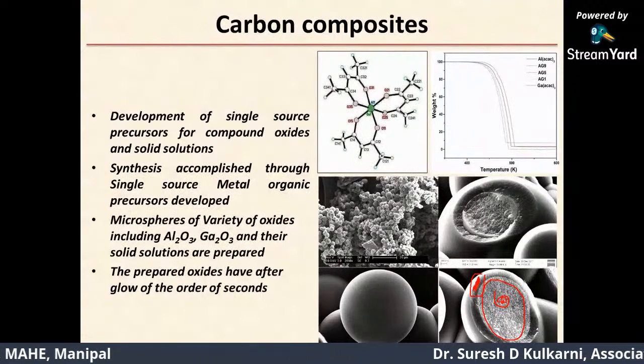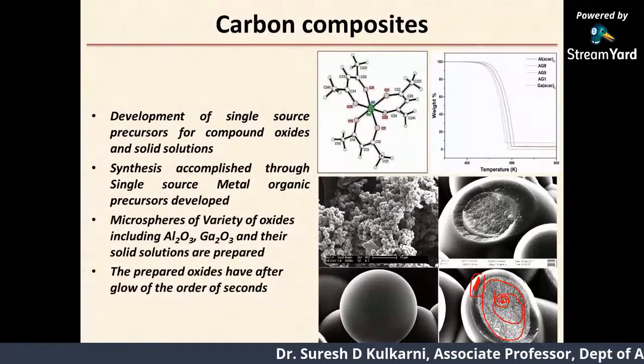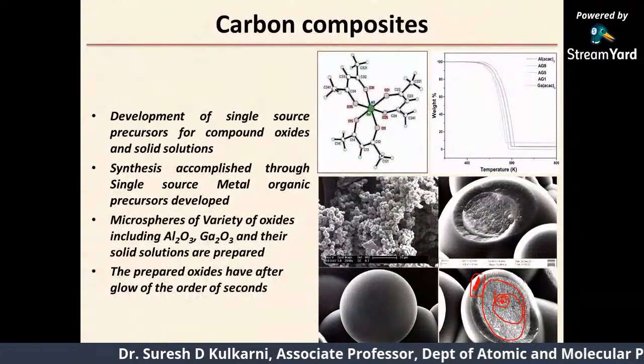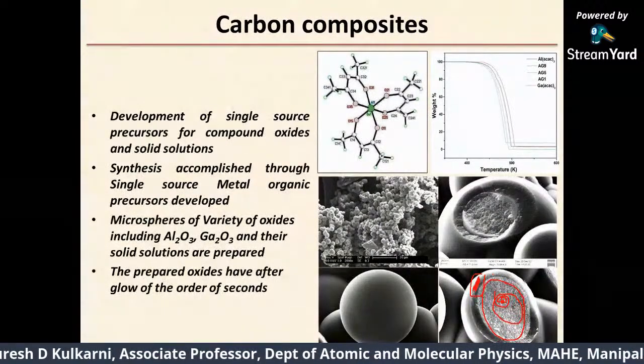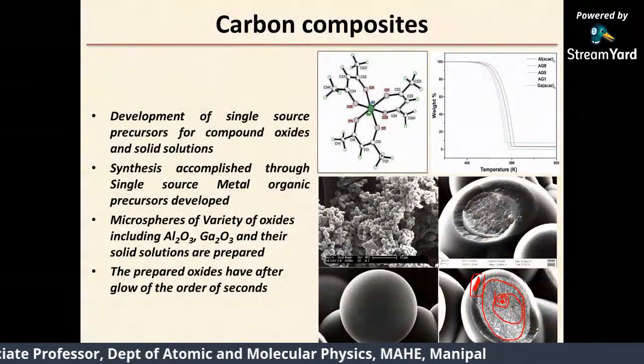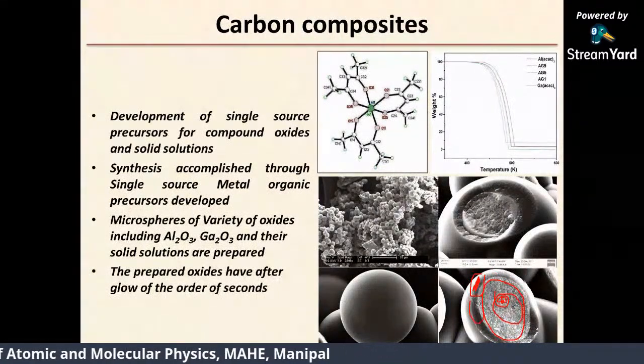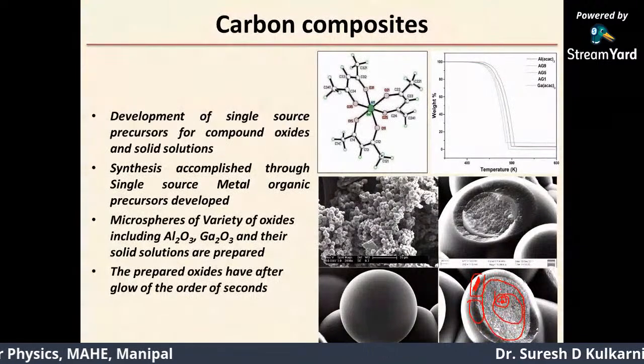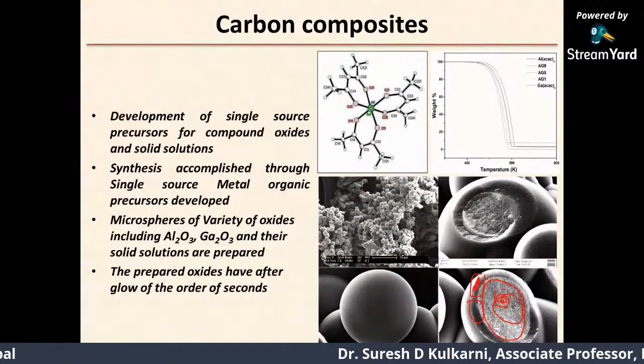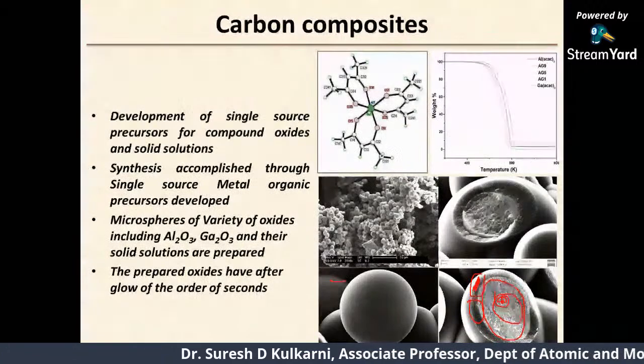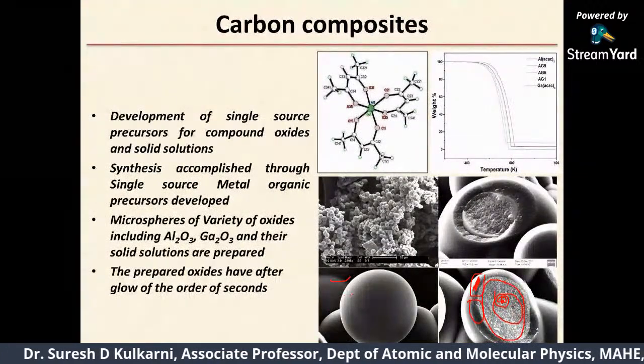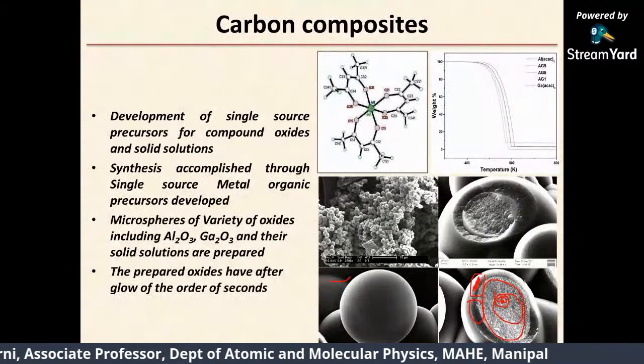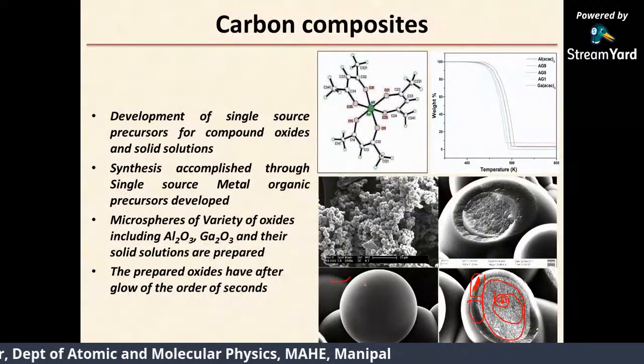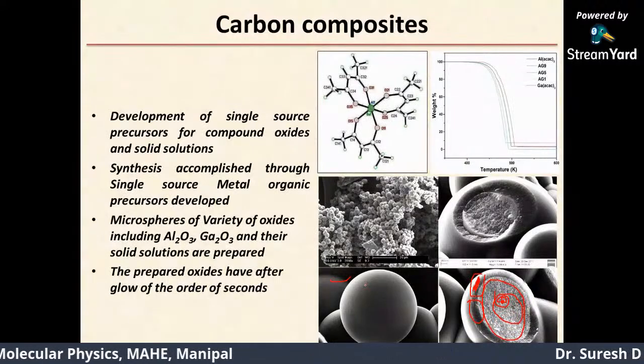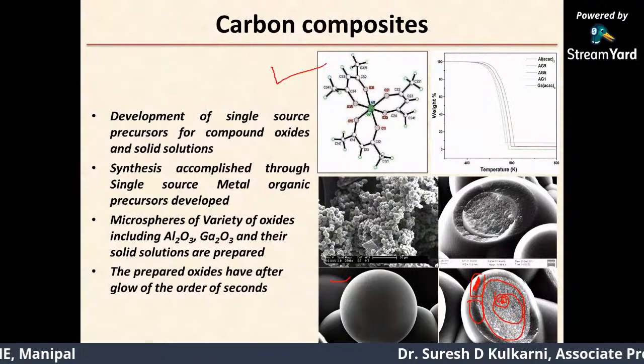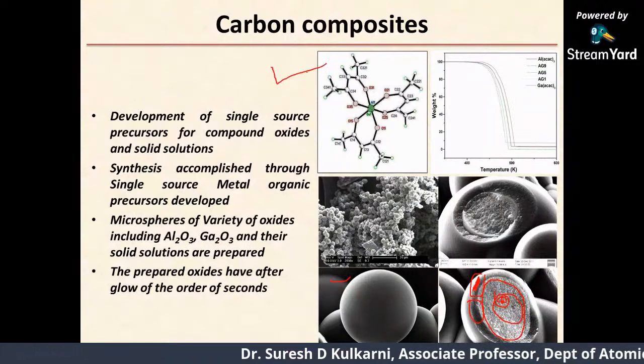So therefore, in the interior, I have aluminum oxide with a small amount of carbon, and outside I have a carbon coating. And if I just heat it in the presence of oxygen, I am able to get rid of this shell, and I am able to get nanoparticles, spherical nanoparticles. You can see the shape, how symmetric they are in this picture. They are quite spherical, nicely shaped, and this process takes only about 1 hour for me to prepare nice nanoparticles. All that you should have is a judicious starting material. In 1 hour of the process, you can form the material.